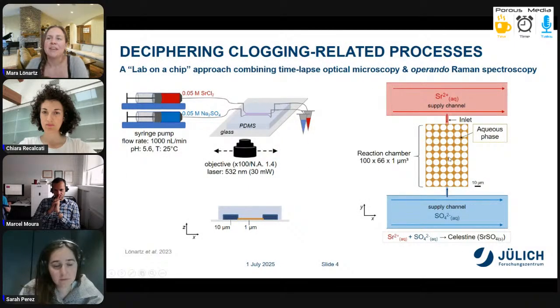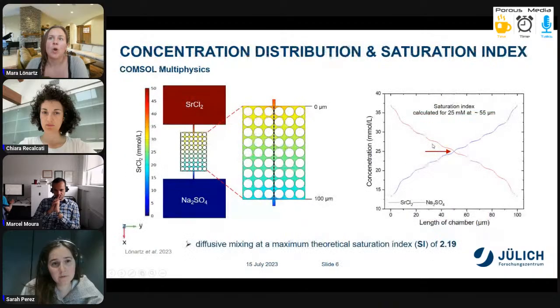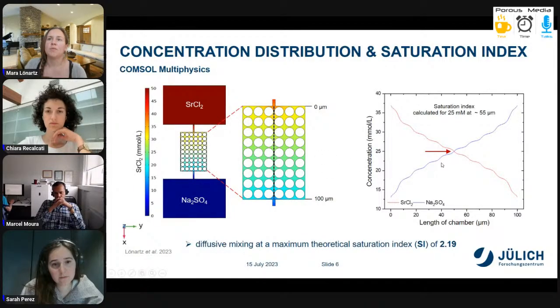Before this, I conducted some computational physics to estimate what concentration is actually needed. So what is the saturation index inside the chamber? You can see here the concentration profiles of strontium chloride and sodium sulfate. We can estimate that in the center region of our chamber we have a concentration of around 25 millimole per liter, which results in a saturation index of 2.2. So this should be high enough to trigger the precipitation.